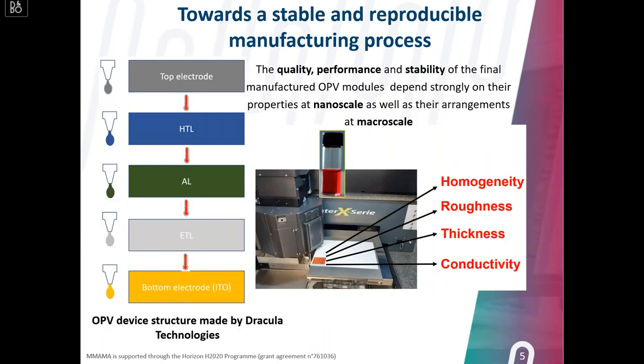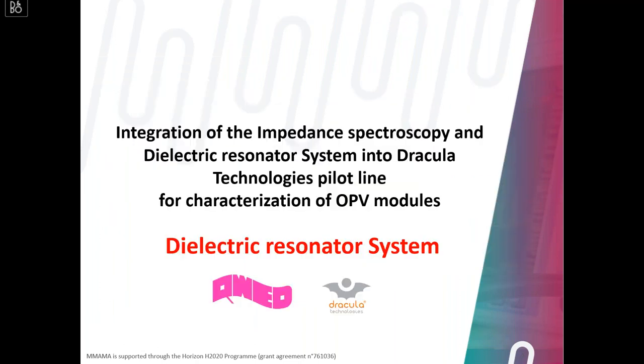So why is it important to have homogeneous and smooth layers, and why do we have to control the thicknesses and the conductivity of these layers? Because it is the most important condition in order to guarantee the performance and, of course, the stability of the devices. And as we have thin layers, in general between 30 and a few hundred nanometers, we really need to be careful, as at this scale we have different phenomena which can degrade the performance if we don't have control over the different layers.